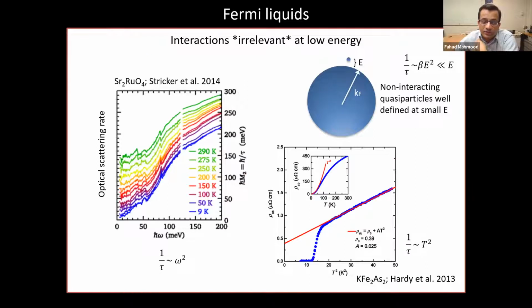We know that that is the case for your classic Landau Fermi liquid theory, where even though you have a full Fermi surface, and even though you might have some interactions, your emergent quasi-particles essentially behave as non-interacting electrons. There are ways to confirm that: by using the optical scattering rate, which behaves with frequency as omega squared, or by measuring the resistivity as a function of temperature, where you see this characteristic T squared behavior. Okay, so that would be your classic metals. However, I just want to point out that these are indirect methods. There are always some assumptions that you're making when you extract the scattering rate from linear optical spectroscopy. In the case of resistivity with temperature, it's not clear whether the scattering rate is actually directly proportional to resistivity.